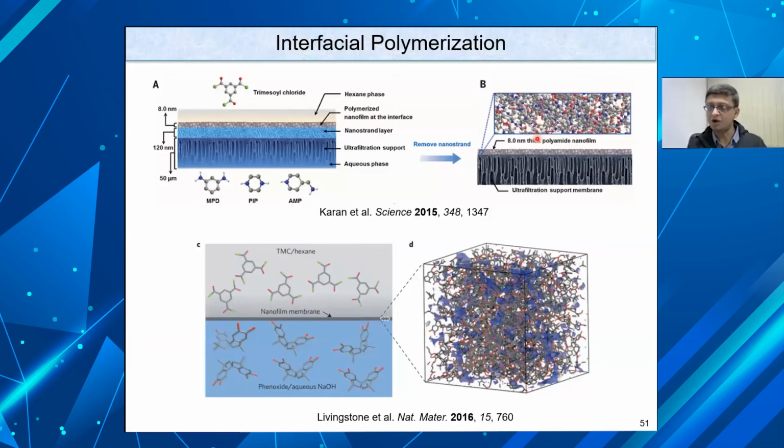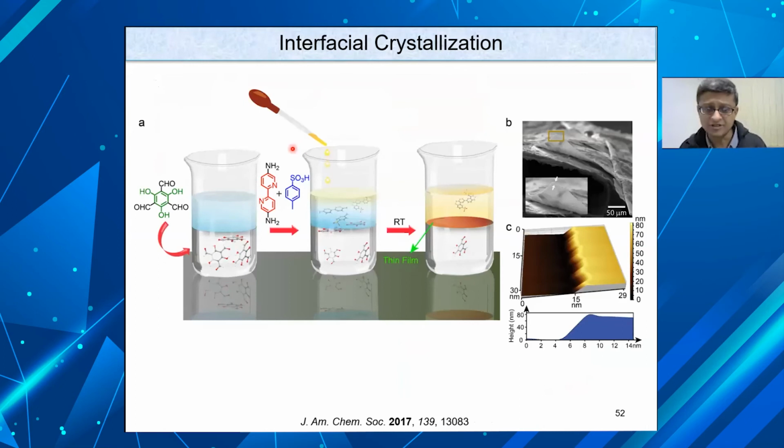So that's when we thought, let's take the help of a simple polymerization technique, the interfacial crystallization or interfacial polymerization, and make these thin films into bulk. Very simply, we took the aldehyde, added some water on top of it, and after that added the amine, and slowly let the aldehyde and amine react. Because it's a Schiff-base condensation, the reaction is reversible. At the first step, you will get these nice thin films, as you can see.